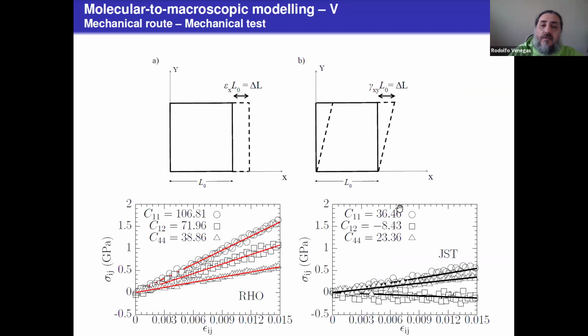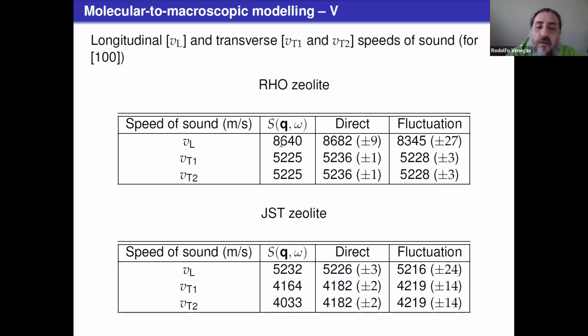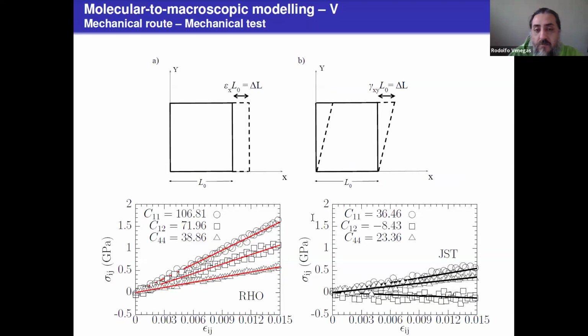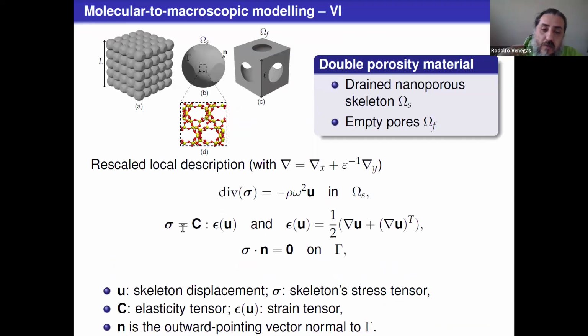This table shows the comparison of the longitudinal and transverse velocities obtained from the three different methods. They are pretty similar, all of them, for the zeolite and also for the JST zeolite, the two materials that we investigated. Once we have these elastic parameters and densities, we can use them as input for continuum-based models. In particular, here we have a double porosity material. This is a consolidated array of spheres that are nanoporous and elastic. For simplicity, we started by considering empty pores, meaning no fluid is filling the material. We are therefore interested only in the elastic waves that propagate in this double porosity material.